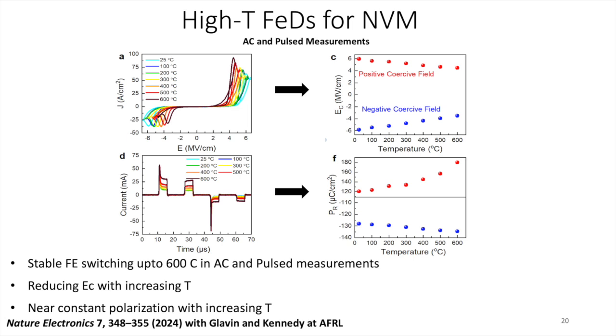So again, proving without any iota of doubt that this is indeed ferroelectric switching that is stable up to 600 degrees Celsius. I should mention again, in unpublished data, we have demonstrated the same thing to happen all the way up to 900 degrees Celsius in these same devices. In the coming months or so, we will also end up publishing that data. But yeah, the 600 degrees C is the published value, but technically, as I said, you can keep jacking up the temperature. At the time, our capabilities to measure were only until 600 degrees C. Now we have capabilities to measure up to 900 degrees C, and we have seen stable ferroelectricity up to 900 degrees Celsius in these devices, and information retention for very long periods as well.